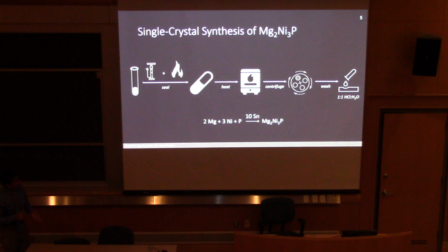The initial procedures are kind of analogous to what we did for the powder synthesis. We combine a 2 to 3 to 1 ratio of magnesium, nickel to phosphorus. However, in our liquid, we actually use tin as our solvent. Tin has been shown to easily dissolve magnesium, nickel, and phosphorus at a design composition. However, as I showed previously, that was actually a binary phase diagram, whereas over here we have 4 substances, which makes it complex, which once again makes us have to use a trial and error method.